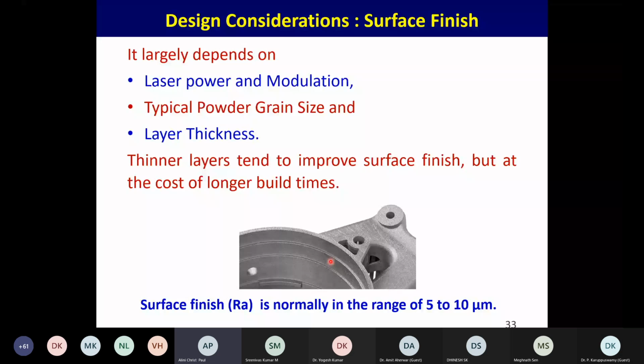Besides this, there is a matter of the surface finish, which can be controlled by modulating the laser power, by changing the grain size of the powder, by changing the layer thickness. So these are the areas, and the typical surface finish that people get is in the range of 5 to 10 micron Ra.